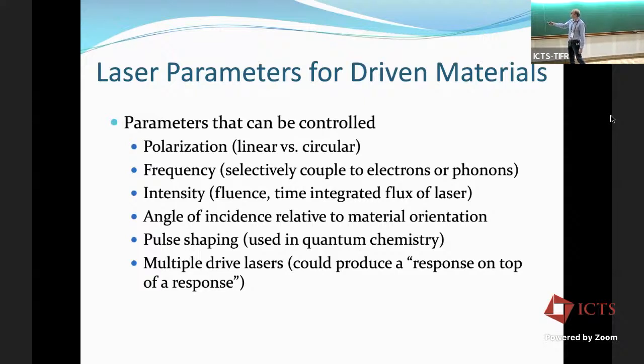So you can change the polarization of light. So you can have linearly polarized light, you could have circularly polarized light, you can have a linear combination of the two, some elliptically polarized light, but these linear and circular regimes kind of represent two extremes. So linearly polarized light will preserve time reversal symmetry in the system, whereas a circular polarized light, which has a certain helicity associated with it, when it's incident on the material, then the combined material plus the light will always have broken time reversal symmetry.